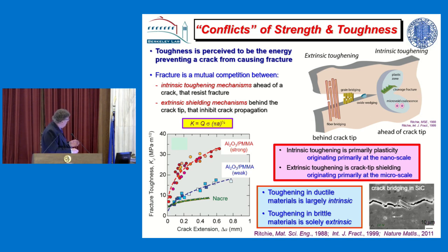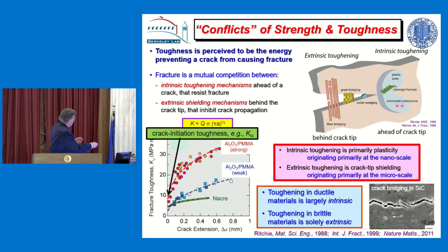So most people think in terms of the crack initiation toughness. I'll talk about K1C, which is the stress intensity to initiate a crack. That's the fracture mechanics way of doing things. But of course, there's all this resistance after the crack initiates, when the crack is growing very slowly, and that's what I call crack growth toughness. Both those mechanisms are very important, as long as the cracks remain fairly small. This, I think, is one of the essences of fracture, that you can initiate a crack and then you can let it grow, but in a rather stable fashion.